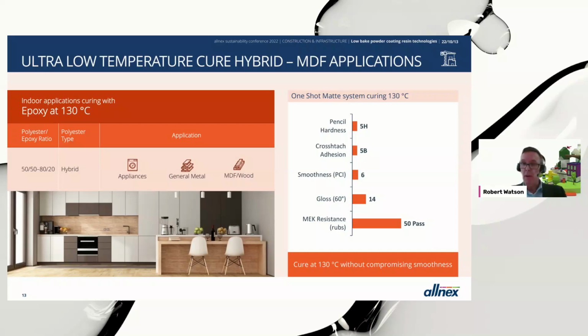And the key point here, if you look on the chart on the right, that middle bar of smoothness, PCI is a Powder Coating Institute test reference, if you like, from 1 to 10. 6 is absolutely what we expect to see with a powder coating that cures at 180 to 200 degrees centigrade. So to get that level of smoothness at 130 degrees is a real, let's say, achievement in what the technology can do.